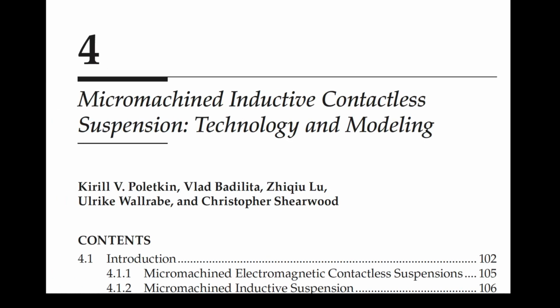Now, moving to micro-machined inductive contactless suspension technology. MIS enables frictionless levitation of microobjects using inductive forces generated by microcoils and eddy currents in conductive proof masses. It's a passive suspension relying on physical properties, avoiding complex active control systems, which reduces friction, extends motion range, and lowers energy dissipation. Microcoil fabrication includes planar coils via surface micromachining and advanced 3D microcoils using SU-8 pillars and automatic wire bonding.